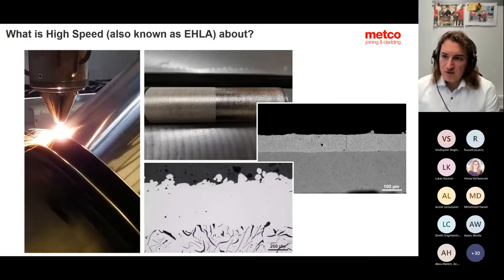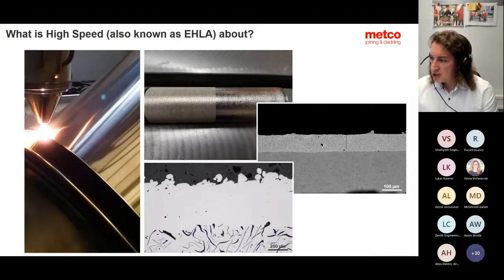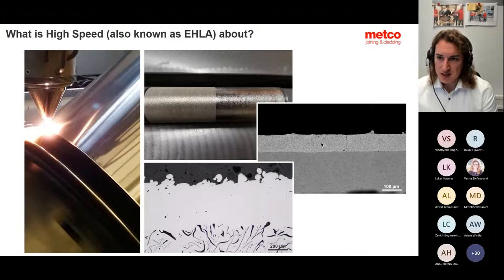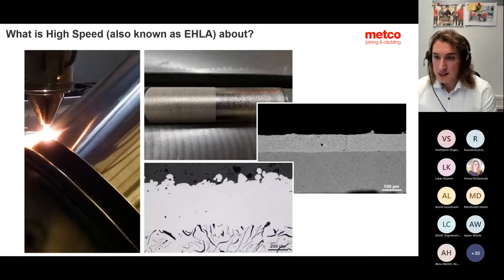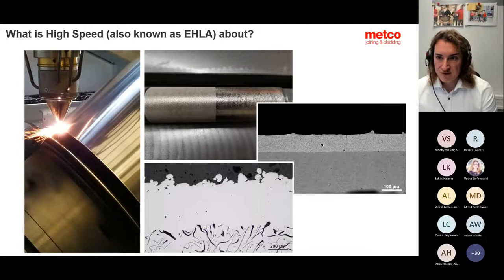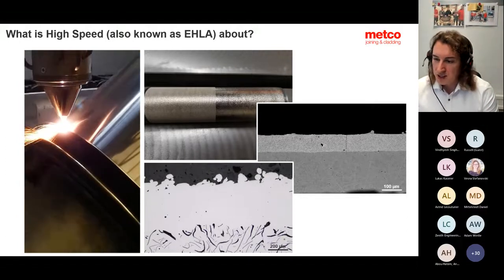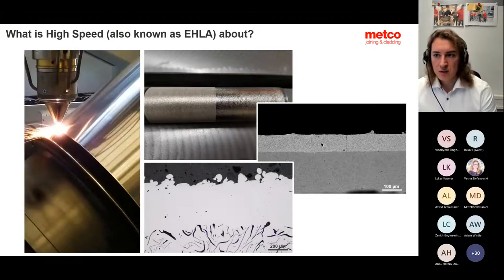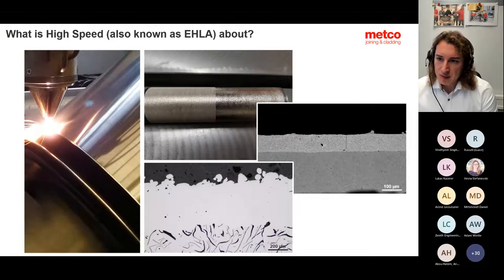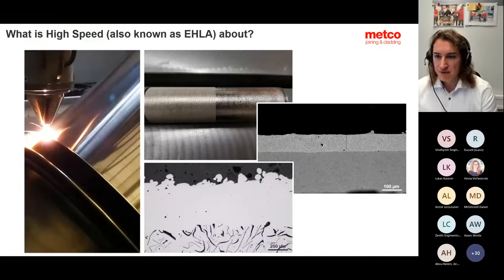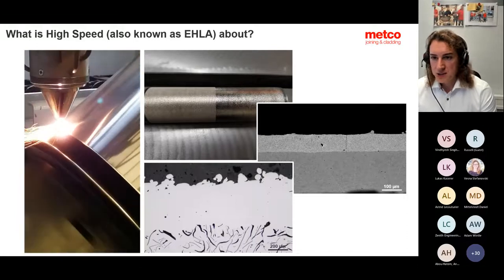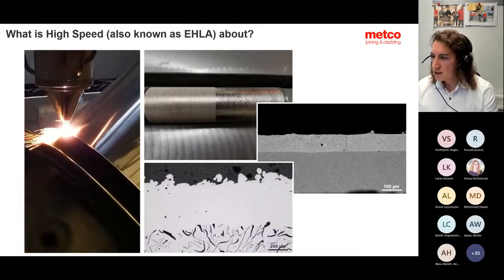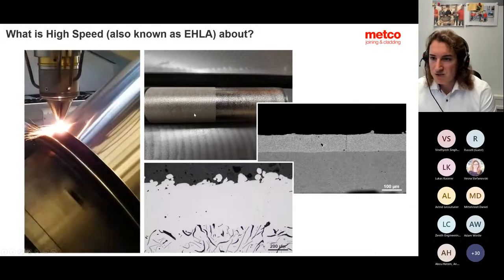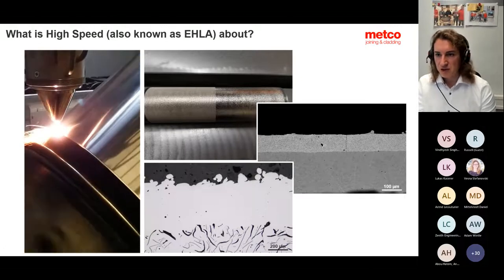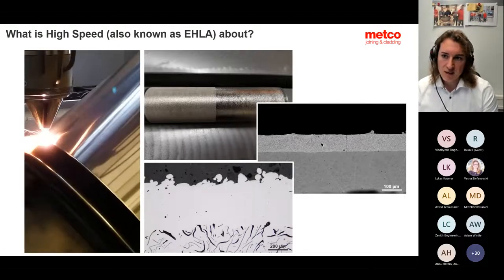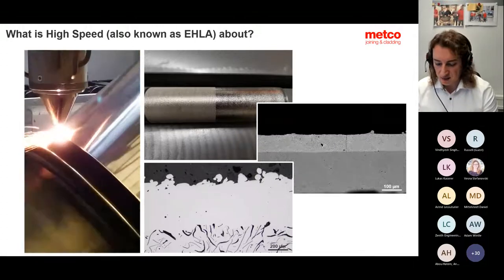There are a couple of other advantages if you work with a high speed process and high deposition rates. First of all, your heat affected zone is even smaller compared to conventional laser cladding. Secondly, you have less interaction with the substrate, which helps you if you want to directly deposit one layer on, for example, hard substrates, castings, gray castings. And last but not least, your surface roughness is impressive. You can see on some pictures that we get really low roughness values, which, if you're familiar with thermal spray technology, have more or less the same quality as you would get with HVAF.